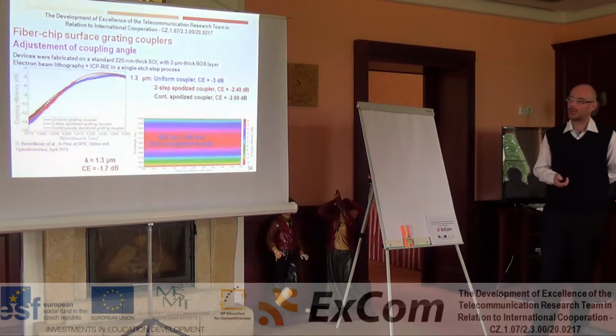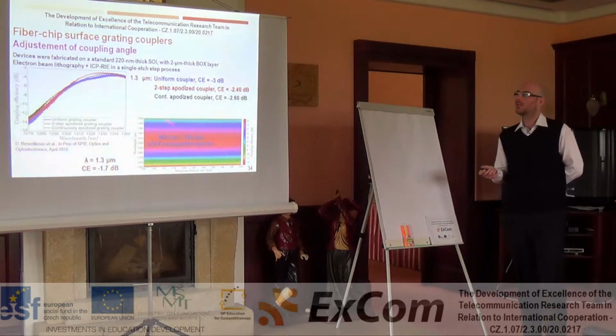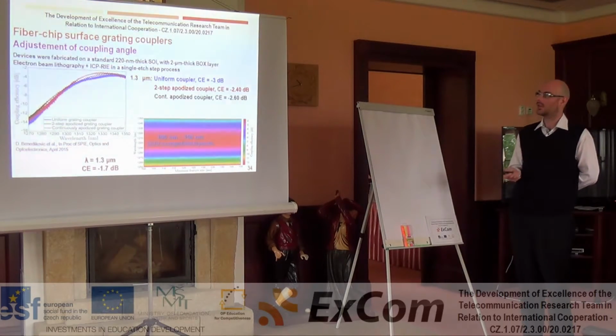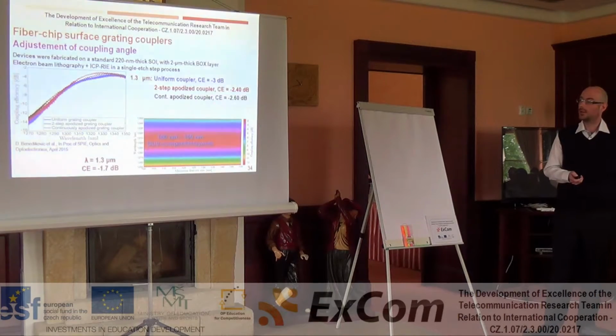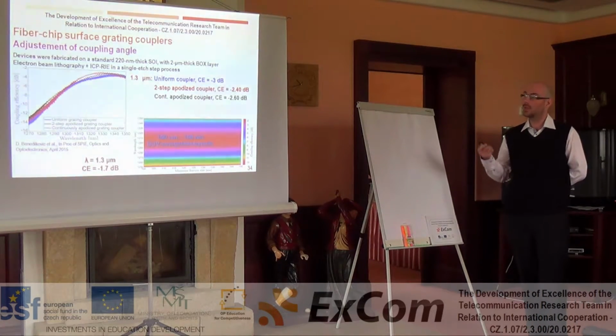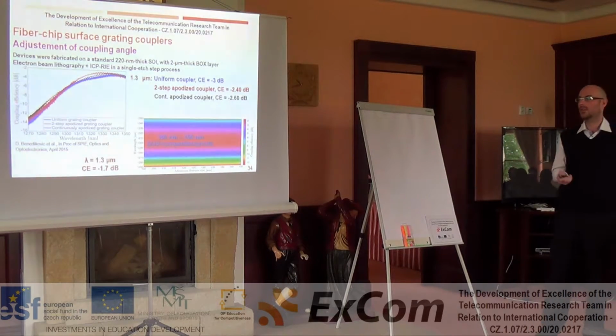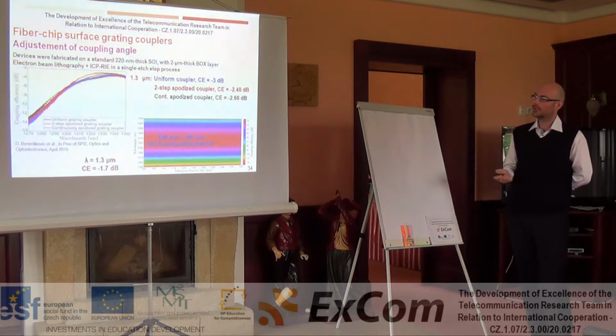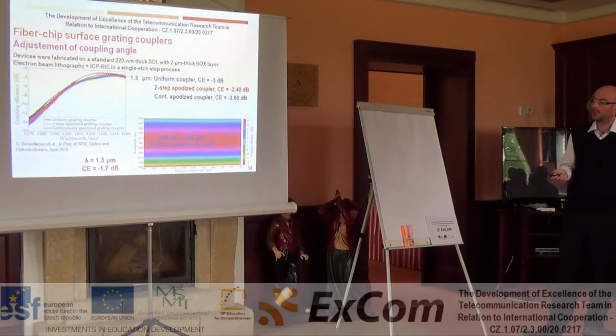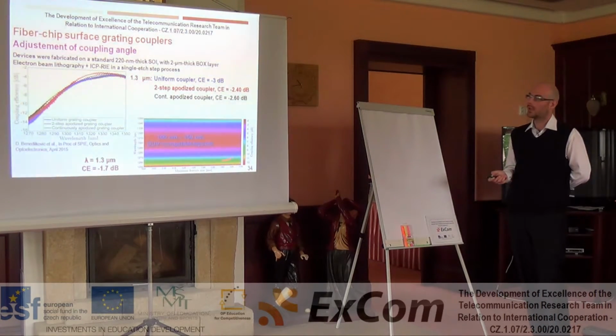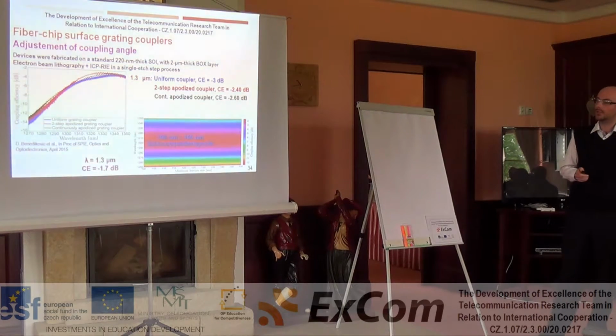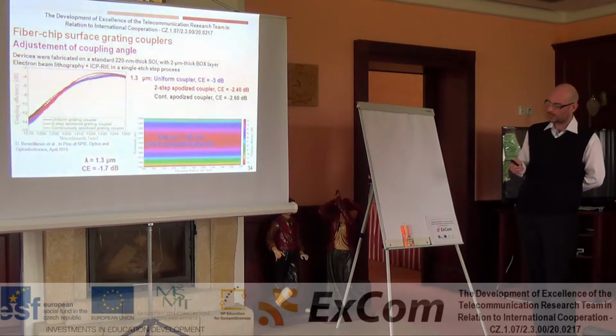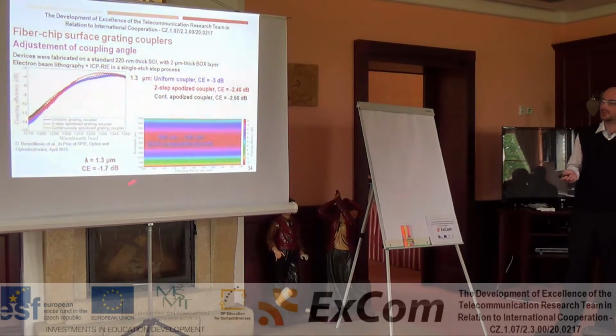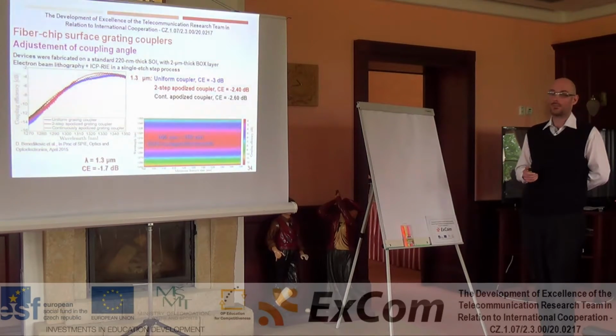We used a similar principle for grating couplers implemented for the 1.3 spectral region, and also we achieved very nice coupling efficiency. The similar coupling efficiency has been achieved for a more complicated coupling structure. In addition, we performed some additional calculations to be sure that this concept will be compatible with DUV fabrication tools. Our calculations predict very high coupling efficiency at the level of -1.7 dB, which is pretty impressive for single-step grating couplers.